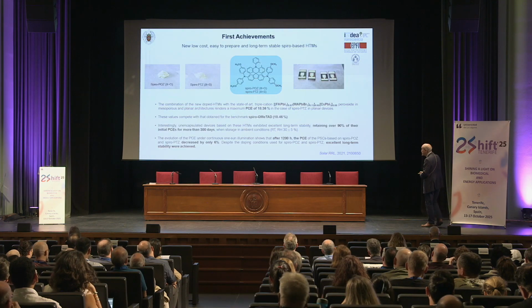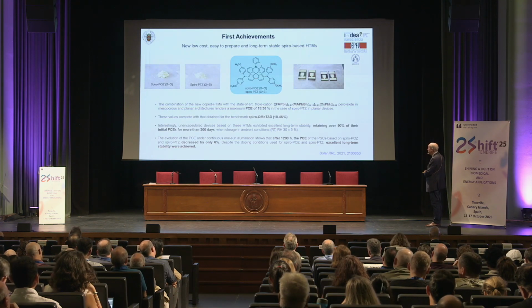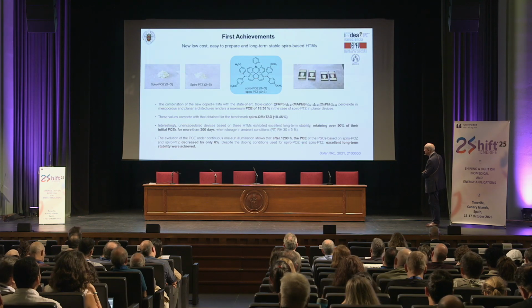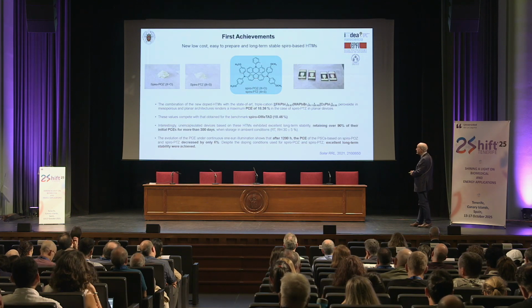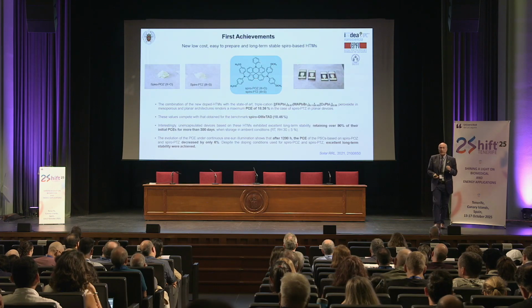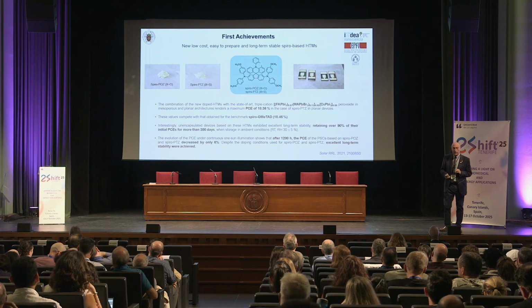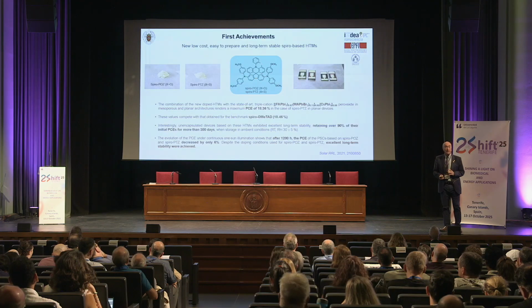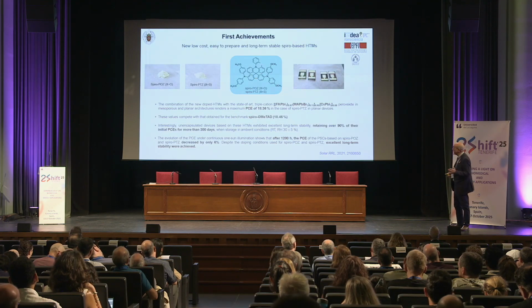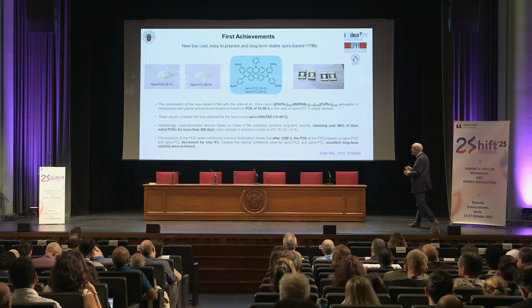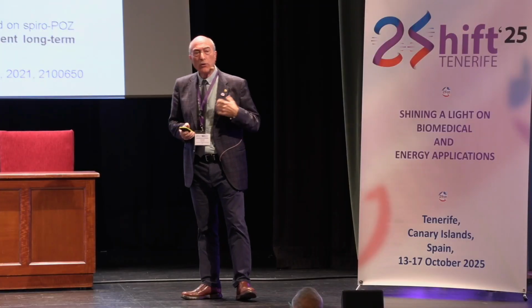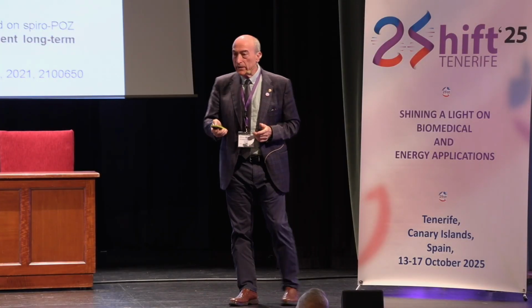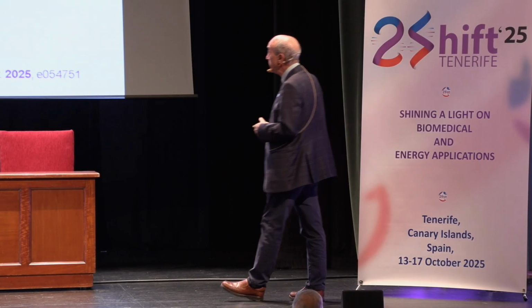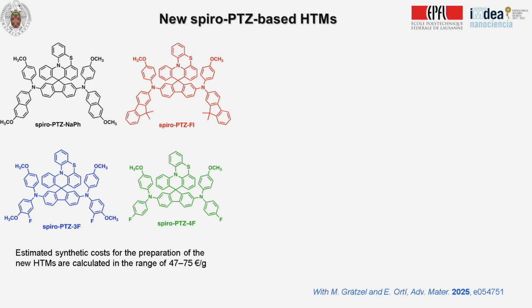And the evolution under illumination was after 1,200 hours, okay? The efficiency also decreased only by 6%, so it retains 94% of efficiency. These were really fantastic, okay? And these were materials by design. But this was the first round. So why don't we improve the quality of these systems? And that is what we did, and these are the new Spiro systems.